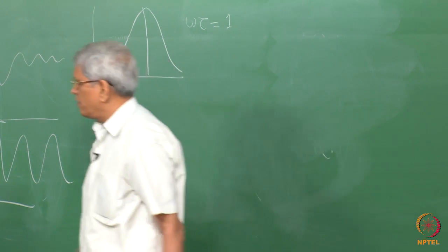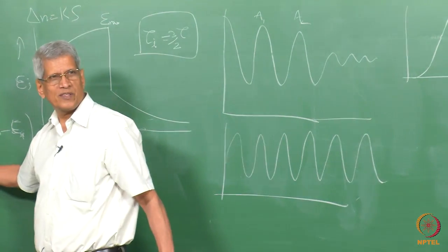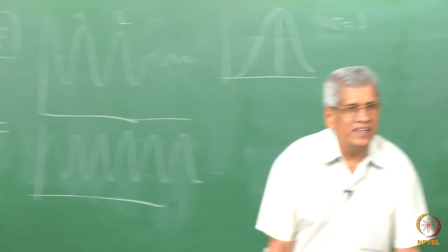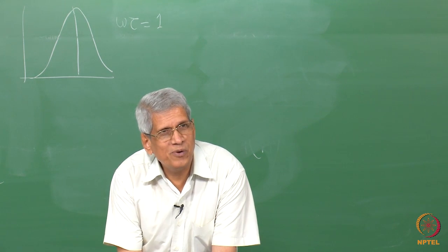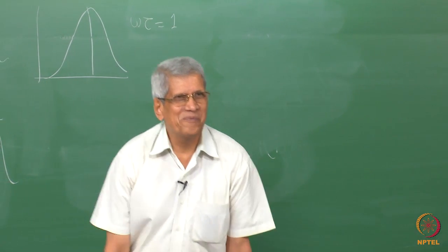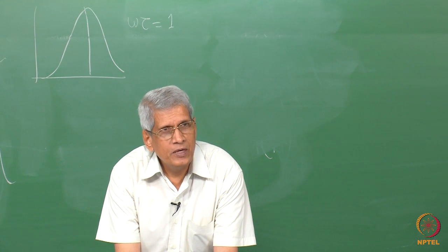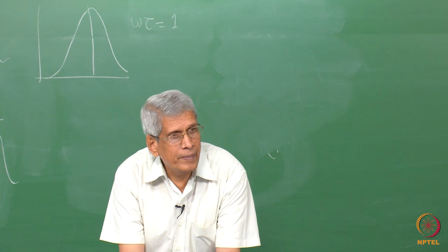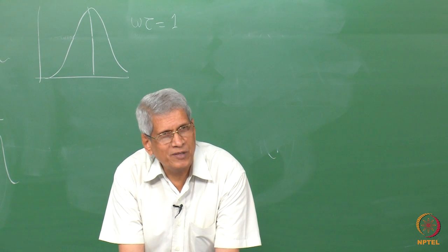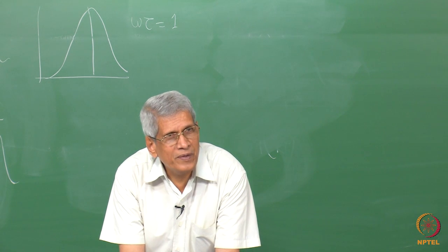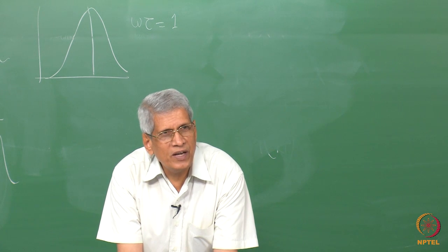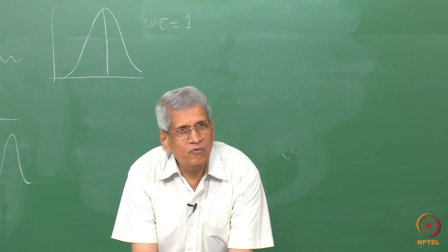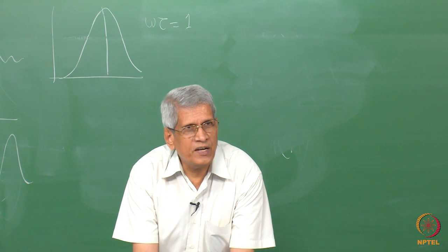Now we are looking at one. What are the possibilities with respect to other phases? It could take place with respect to this direction. There are three possibilities which exist, correct? So when this defect has to move, it can move like this, like this, like this. It will have a different way in which it will be moving, correct? This will be a coupled movement. Similarly, not only a single interstitial, suppose it's a complex which is moving, then it will have different jump rates. So by doing this experiment, from the migration energy we can get indirect information about the structure of that defect configuration itself.